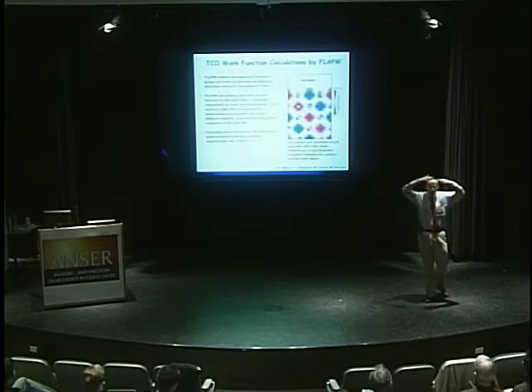And Art calculates for 9 layers of nickel oxide. Here's the electron density on a surface. He calculates a work function of 5.62. And then Ben Lever, who's a student with Mark Hersom, jointly with myself, and actually Mike Durstock at the Air Force Laboratory has a very fancy photoelectron spectrometer, and they get 5.040 for the work function. Art gets 5.62. The nice thing here is we're really going to be well equipped to design new materials. And another really interesting thing is what happens now when you do a calculation with a layer of organics covalently linked to that surface. And that's one thing we'll do under ANSER.